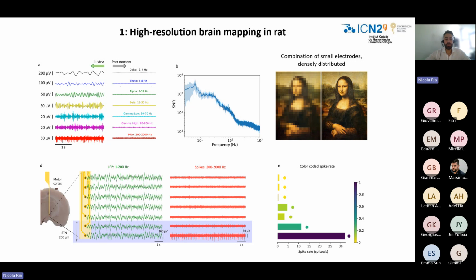But the subthalamic nucleus also has a very particular signature in the activity, and it has a very intense spiking activity, while the regions before and after are silent. So by looking at the brain activity in this frequency range, we were able to position two electrodes in the subthalamic nucleus, the ones you can see in the red trace that are more active, while the others are silent.